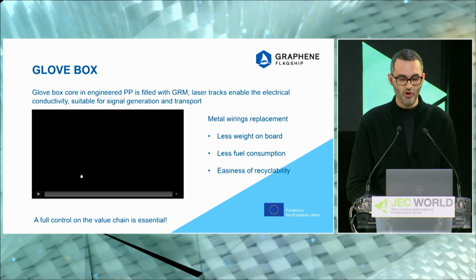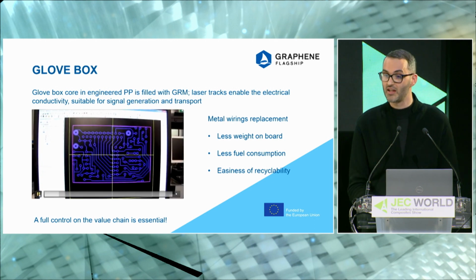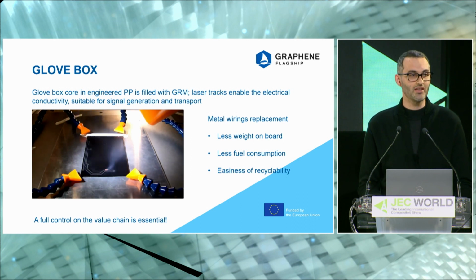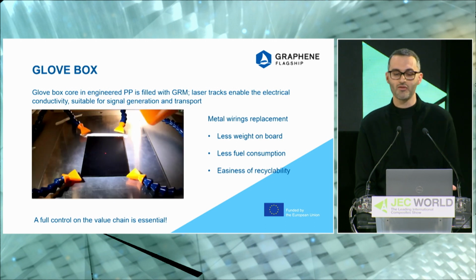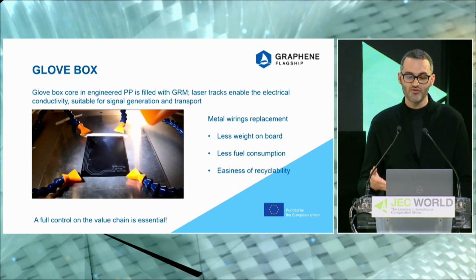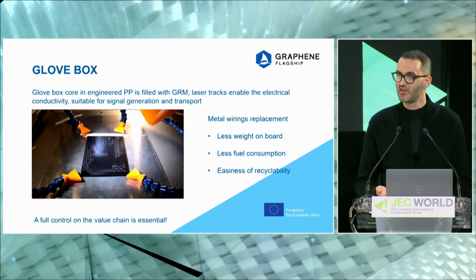If you put a small amount of graphene inside a thermoplastic material, you won't change its mechanical, thermal, or electrical properties, because it is very difficult to disperse the graphene inside thermoplastic. But if you activate part of the material with a laser track, like in the video that I'm showing, you can write an electronic circuit directly on the plastic. In the tracks, the polymer becomes conductive, and you can build an electronic circuit directly on the plastic. No metal, nothing else, completely recyclable. And in fact, you have a metal wiring replacement, so you have less weight on board, less fuel consumption, and easier recyclability because everything is plastic.